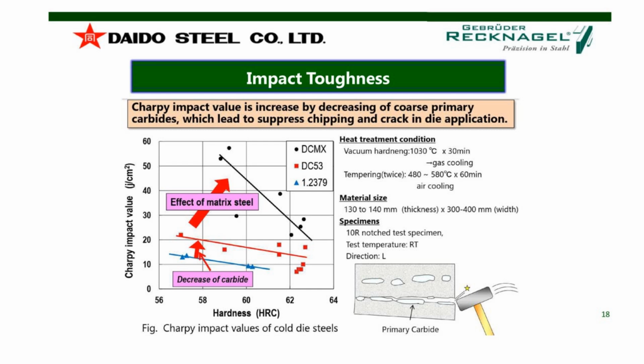The situation with DC53 or an 8% chromium steel is better, much better, because of the finer carbides. But the situation with DCMX is so much different. If you use the highest hardness of 62 HRC, you have more toughness than with the other grades. But if you reduce your hardness back to 60 HRC, you will gain so much more toughness for your punch, for your stamping process. That's outstanding. And the reason is very clear, I guess, because of the very, very fine microstructure without big carbides. You will gain so much more toughness with DCMX.